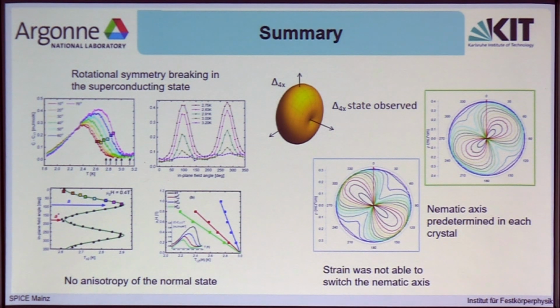So I hope I have shown you that we have rotational symmetry breaking in the superconducting state of these doped bismuth selenides, whereas the normal state shows no anisotropy. We have collected evidence that the Δ4x state in these systems is realized. And we think that there is a strong predetermination of the nematic axis in these crystals. And by strain, by gluing them on glass fiber reinforced plastics, we were not able to switch this nematic direction.